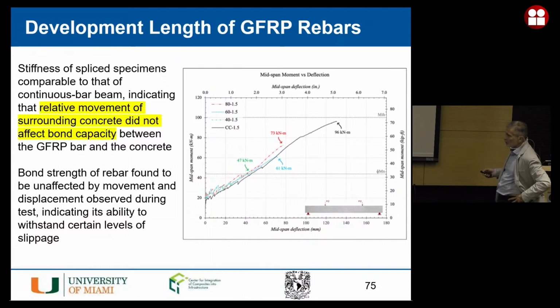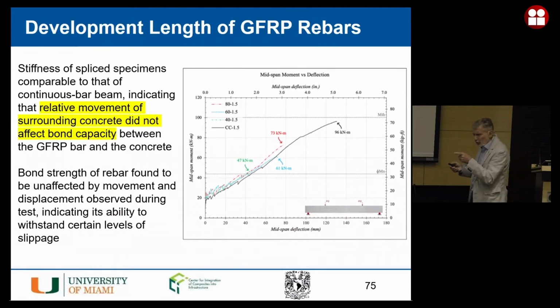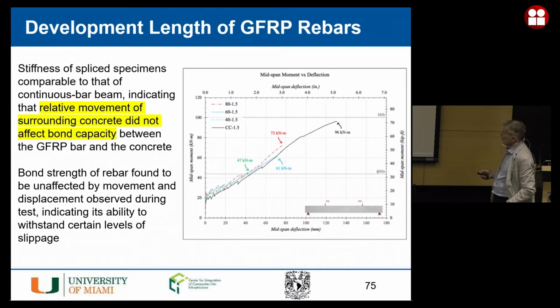You can see they all crack more or less at the same point. By the way, these beams are notched, so we control the location of the notches where the end of the splices is, because we need to understand how the crack location affects capacity. So they all crack at the same point, and then they proceed with the same stiffness. Even the green one, which has a capacity that is less than half of the continuous, does not have a degradation of stiffness. Honestly, I just don't understand it. So help us out. We're still working on it. We have many more beams to look at, but the performance is the same.